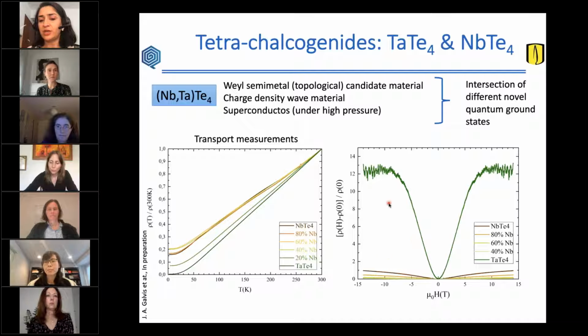Another very interesting observation that we found is that although the evolution of the resistance measurement is not as marked, the evolution in the magnetoresistivity in the solid solution is very extreme, being of the order of 100% for the niobium tellurium 4 compound, but for the tantalum tellurium 4 it is of the order of 1200%, showing very beautiful quantum oscillations that we don't see for the niobium compound.